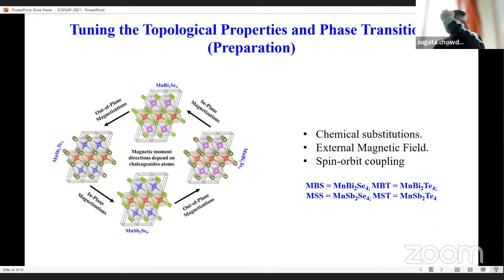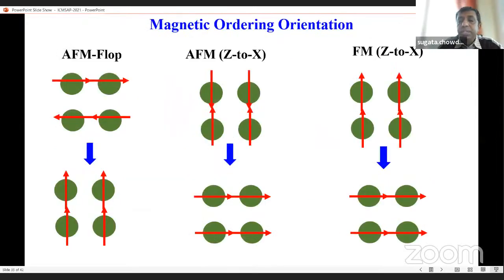The third part, the paper is in preparation now. Until now we have discussed the manganese bismuth selenide structure and the manganese bismuth telluride structure. The question is, if we change the chemical structure, so the chemistry is changing, is it possible to get a similar kind of material? So what we did, we changed not only the magnetic chemistry of the material, we also changed the applied external magnetic field. That means from in plane to out of plane ferromagnetism, from out of plane antiferromagnetism to in plane ferromagnetism, and out of plane to in plane ferromagnetism, how does it work?